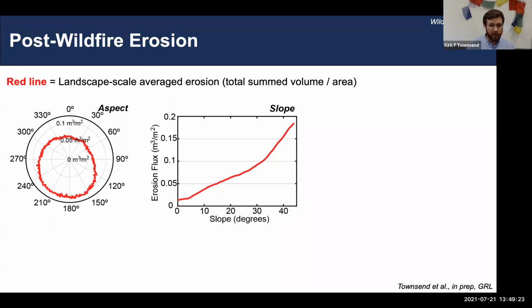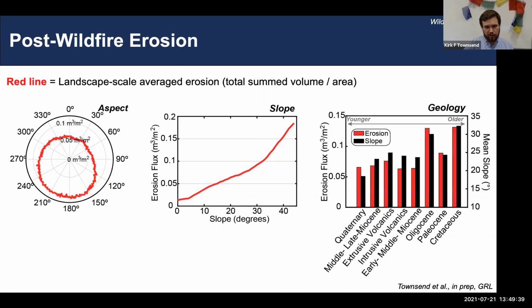We find the second relationship of erosion rate increasing with slope, which is also an expected relationship, right? As landscapes get steeper, they become more susceptible to erosion after you've removed any of the vegetative cover that kind of anchored the soil in place. This last relationship, though, of erosion by geologic formation was a bit more unexpected. So here, the red bars indicate erosion, black bars indicate mean slope, and these are arranged by stratigraphic unit, with the youngest here on the left, and then going to oldest here on the right.